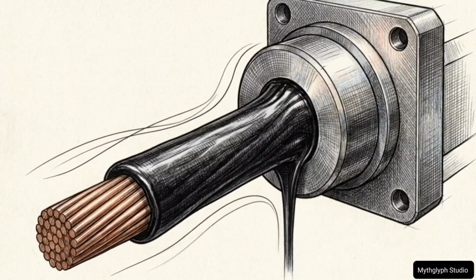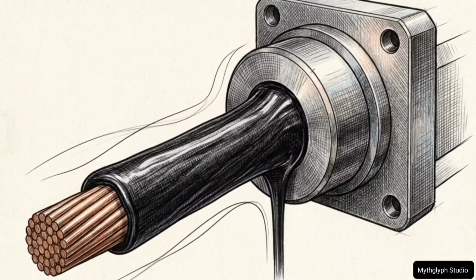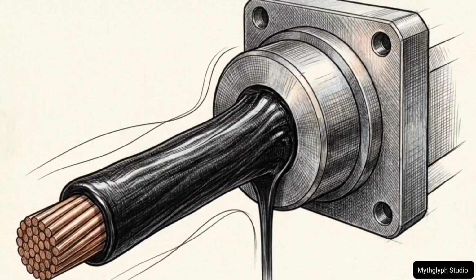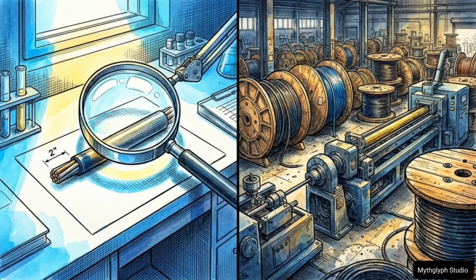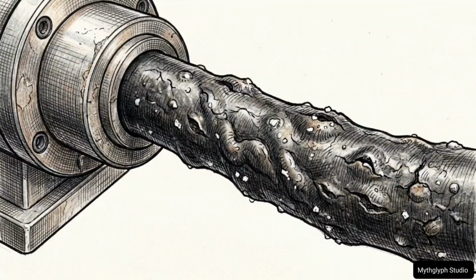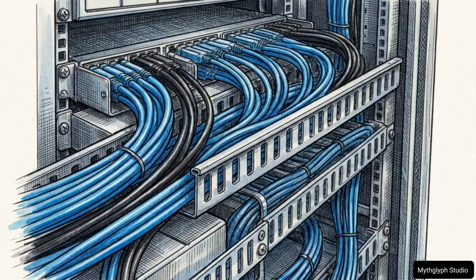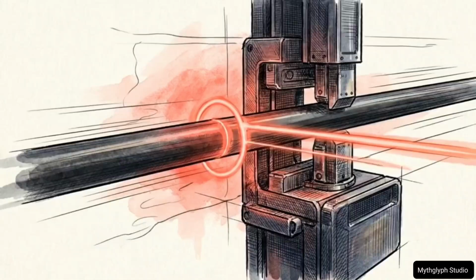The next hurdle is physical manufacturing, pulling a moving core through high-speed, viscous polymer extrusion. A specialized chemical compound that successfully passes an isolated laboratory test does not guarantee a stable, mass-producible product on the factory floor. Heavily loaded flame-retardant compounds are notoriously difficult to run. They can cause severe processing issues on the line, like material plate-out or degraded surface finish. Simultaneously, the space constraints of modern data center modules require these multi-layer constructions to maintain incredibly tight dimensional tolerances.